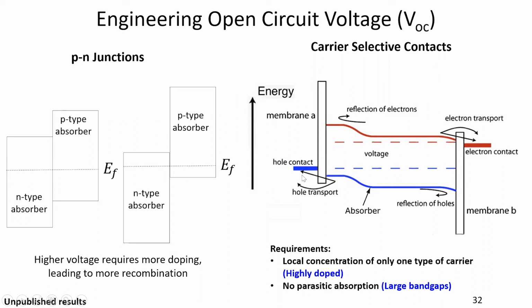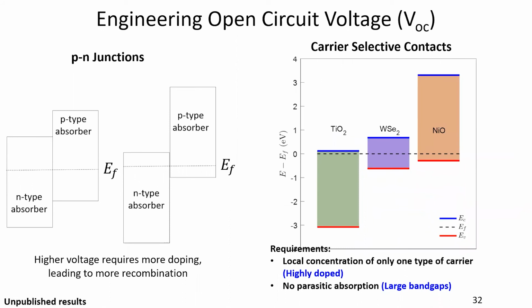And so this is something the silicon community has done very well, and some of the most efficient silicon solar cells have been made this way. So we did a lot of work on this area. Again, I don't want to go through all of it. Most of these results on open circuit voltage are also unpublished, but we have found some evidence that TiO2 and NiO may be reasonable contacts.